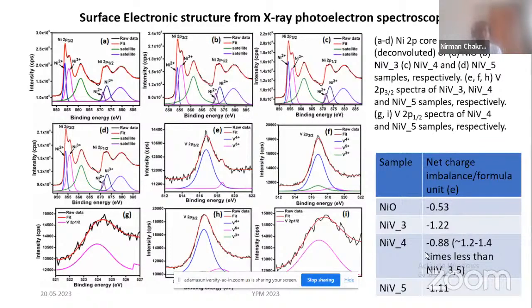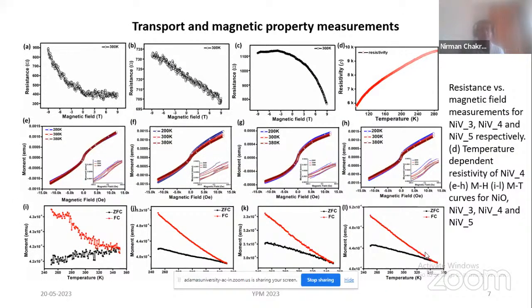Now, nitric oxide is typically an oxidizing gas, and nickel oxide is a p-type semiconductor. However, the question arises whether vanadium doping changes its electronic behavior. So we obtained transport property measurements. We did Hall effect studies, and found that even after vanadium doping, our sample continues to be a p-type material. So we were confirmed that nitric oxide has an oxidizing nature, and on interaction with the surface, it withdraws electrons from the material. Now the composition NiV4 has less excess surface positive charge.